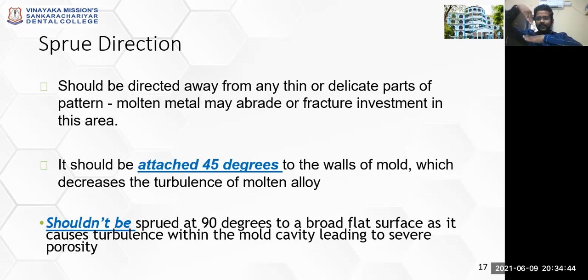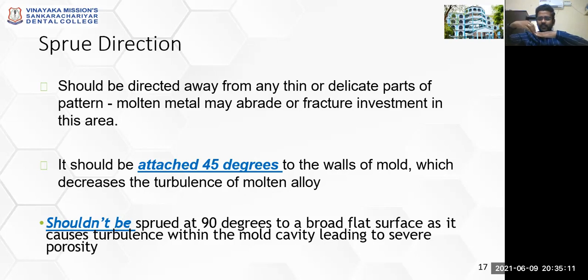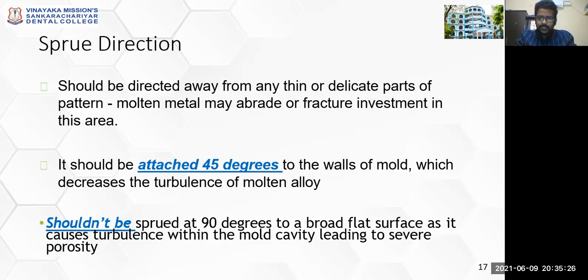The sprue should be attached at an angulation of 45 degrees. It should never be attached perpendicularly at 90 degrees, because when you gush molten metal through a perpendicular channel, this region becomes a hot spot during solidification, creating a high chance of porosity. When attached at 45 degrees, the metal flowing through easily reaches all regions of the mold space. It should always be attached at 45 degrees, not 90 degrees.